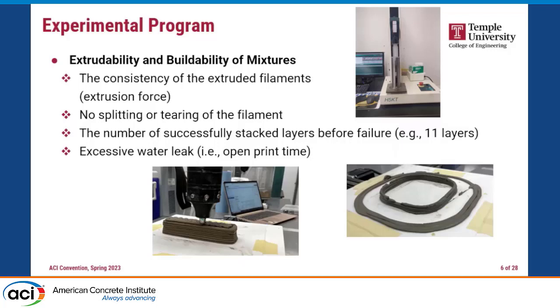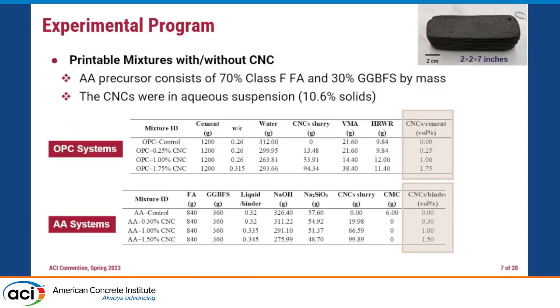The splitting and tearing, obviously you are familiar with this. This is not an acceptable system. And regarding the buildability, we looked at how many layers we can stack. Since we were interested in printing a 2-inch by 2-inch geometry, we printed around 11 layers, and if we didn't see extensive deformation, then that was acceptable for us. Also, in some systems we saw excessive water leaking from the nozzle due to the separation of the material, so that wasn't a printable system either.